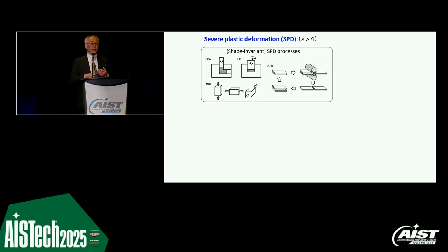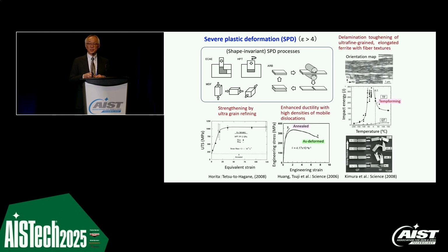So as I mentioned already, in the national project, severe plastic deformation has become more important. So this is, of course, a shape-invariant plastic processing method, like ECAP or high pressure torsion, or multi-directional forging, or accumulated roll bonding. In all of these plastic deformation processes, we can apply very severe, high strain in terms of severe plastic deformation. Epsilon is over 4. So by having such severe plastic deformation, we have very interesting phenomena.